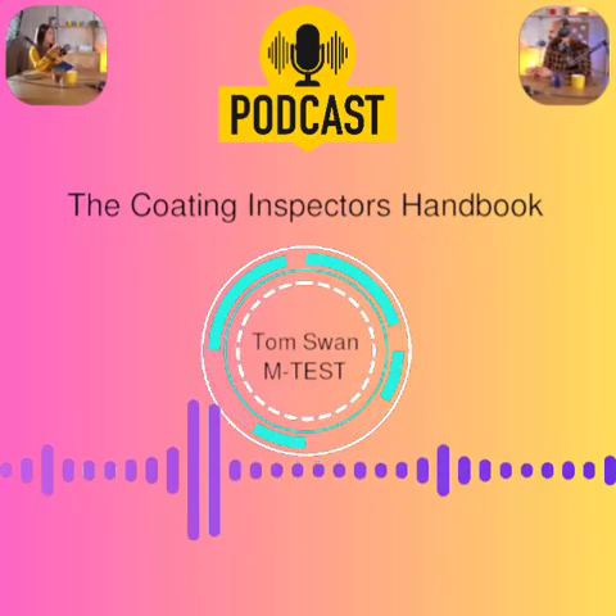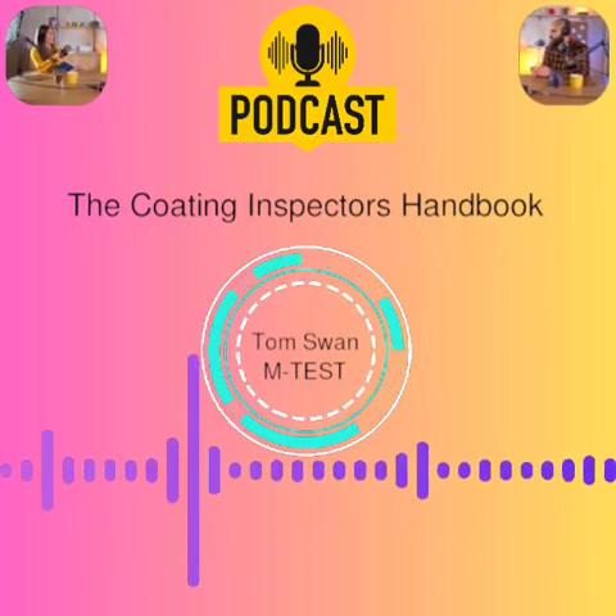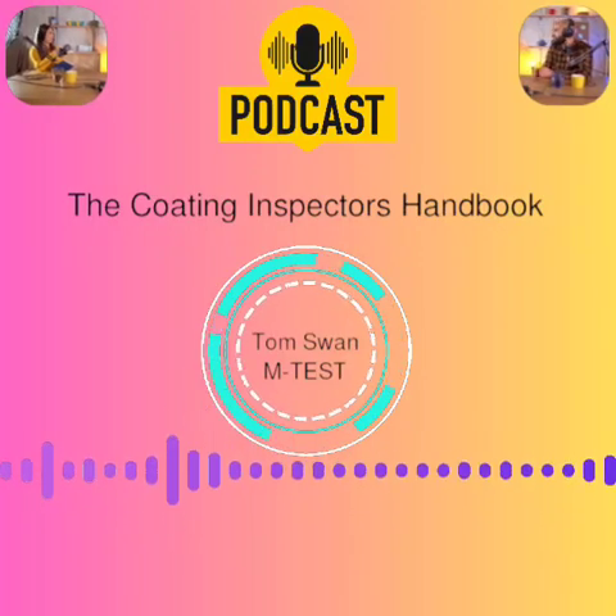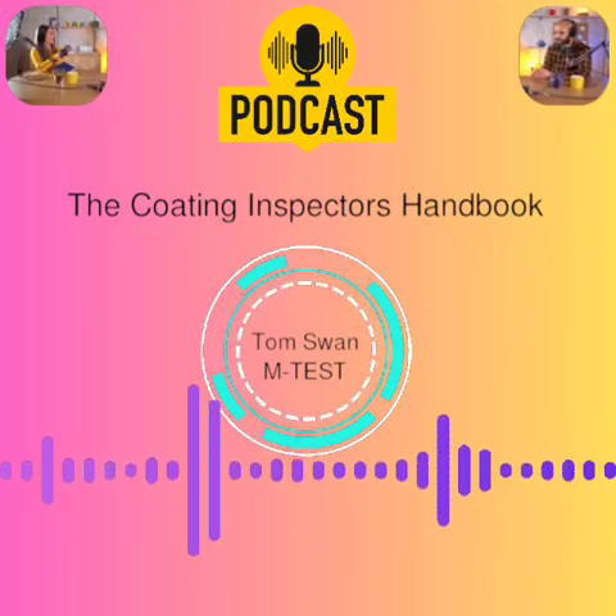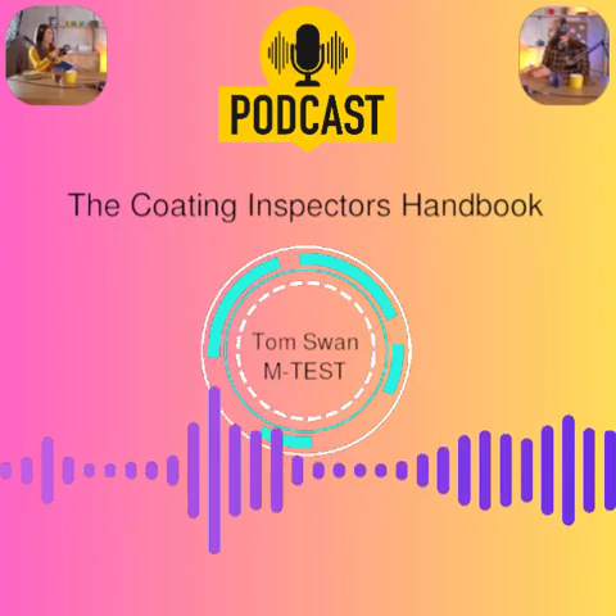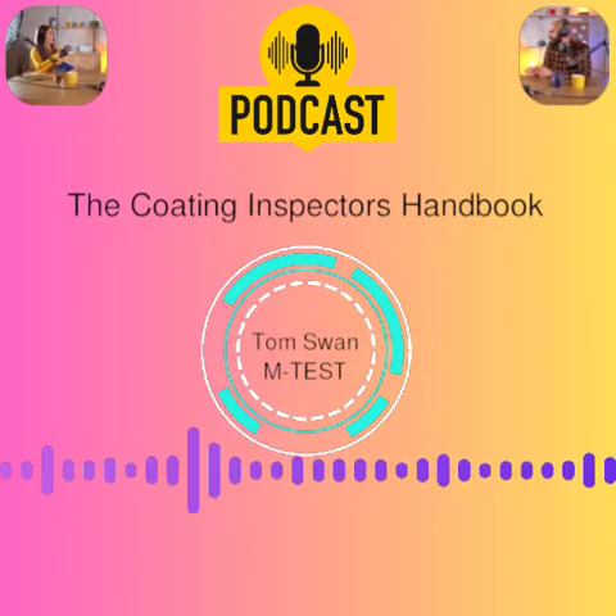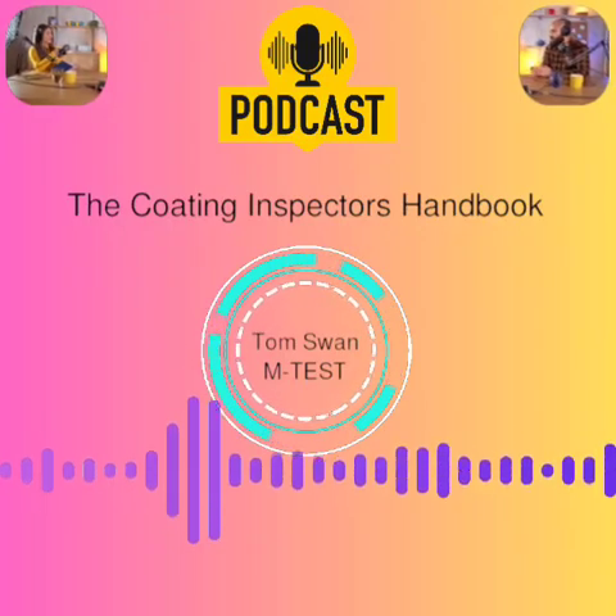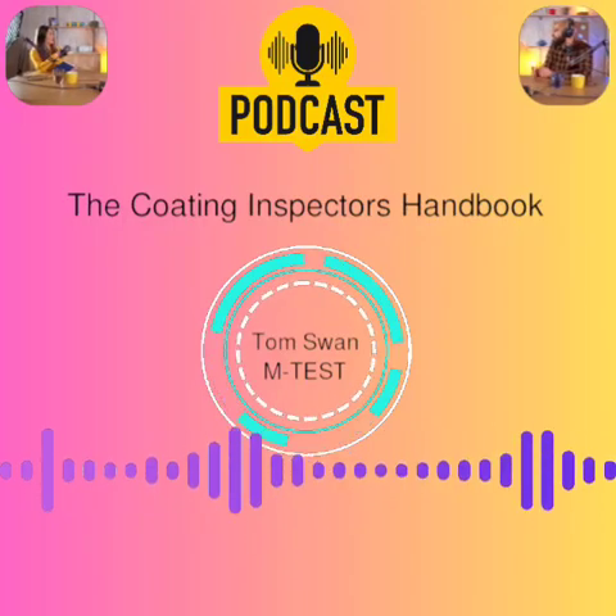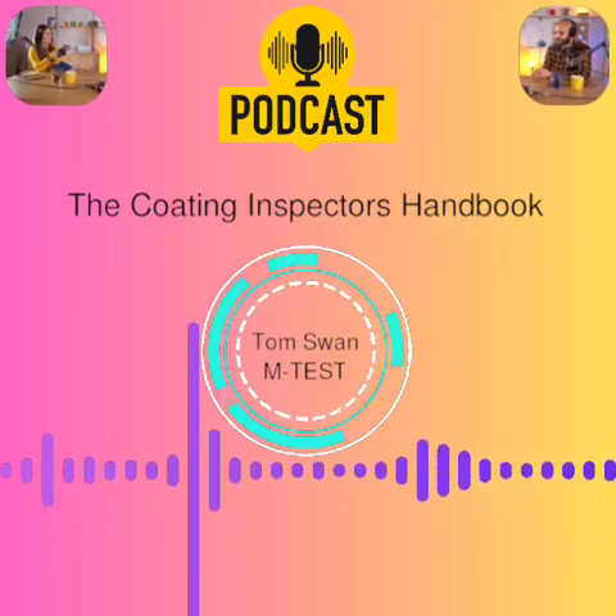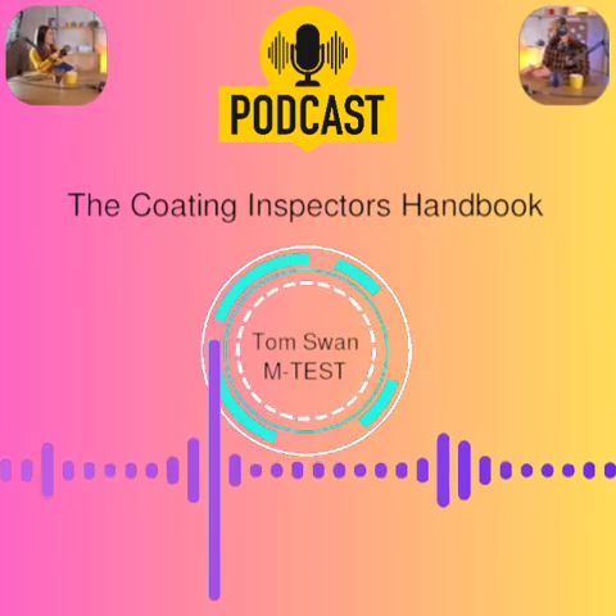That's removing oil, grease, dirt, salts with solvents, or steam. Critical first step. Then the blasting levels. SSPC SP5 is white metal blast, the highest level, free of all visible contaminants, looks bright, uniform. Okay. SSPC SP10 is near white, almost as clean, but allows random staining on up to 5% of each unit area. Unit area being? Usually defined as about 9 square inches, 3 by 3.